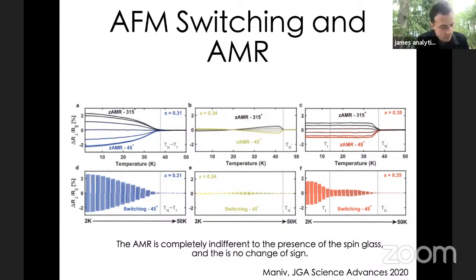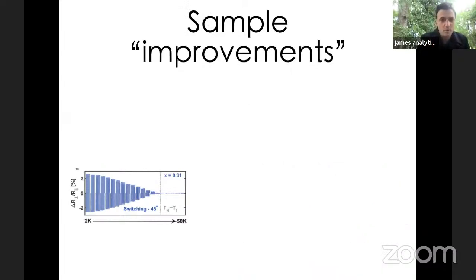Part of the reason why it didn't work is because the way we're fabricating these samples, we use the focused ion beam, which disorders that top layer, because you implant ions basically in machining the sample. So when we first tried it, we basically saw nothing. The second thing, so now we've started to work on samples with our photoemission collaborators, and also our STM collaborators, that you can cleave after the device is fabricated, so revealing a clean surface. And we haven't measured those, but you can imagine it's a bit of a tour de force, because, well, tour de force is maybe a bit extreme, but anyway,